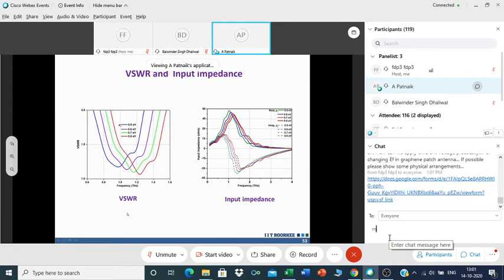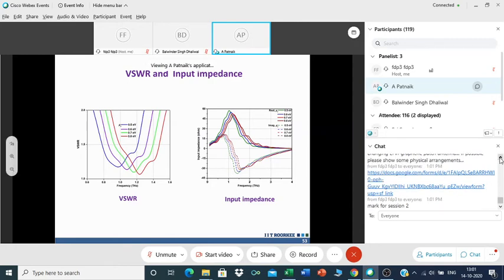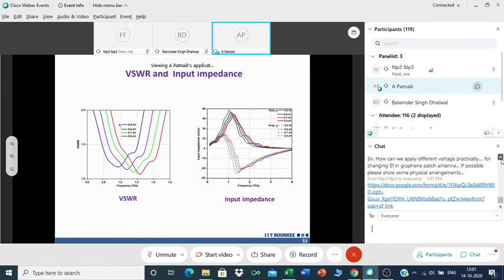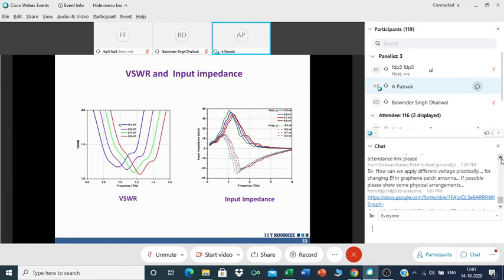And you can mark that because of the presence of that metal layer, in the previous case, it was maintaining that particular input impedance. But because of the presence of that metallic layer, here you can mark that the impedance is also varying. If it is only graphene layer, then it is maintaining that input impedance. But when you are using metal with graphene, then its input impedance is also varying. Okay, that is one thing we have marked.